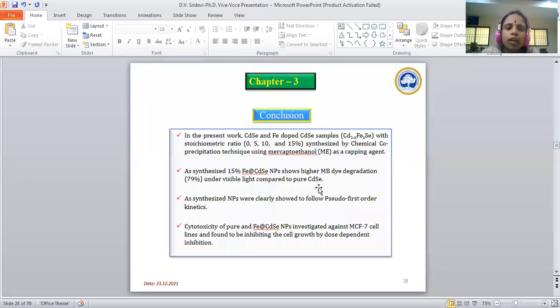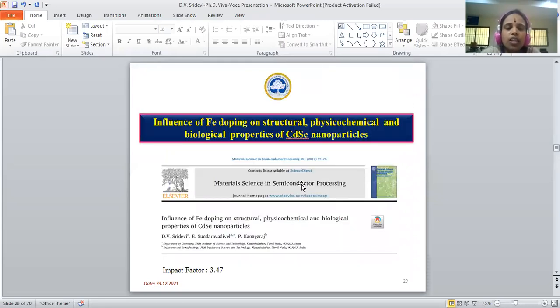Conclusion. In the present work, cadmium selenide and Fe metal doped cadmium selenide samples with a stoichiometric ratio of 5, 10 and 15% have been synthesized by chemical co-precipitation technique using mercaptoethanol as a capping agent. The synthesized 15% Fe doped cadmium selenide nanoparticles show 79% enhanced photocatalytic activity under visible light compared to the pure cadmium selenide. The nanoparticles were clearly shown to follow pseudo first order kinetics. In addition, all synthesized nanoparticles were investigated against breast cancer cell lines and were found to inhibit cell growth by dose dependent inhibition. This paper was published in Materials Science in Semiconductor Processing in the year 2019.